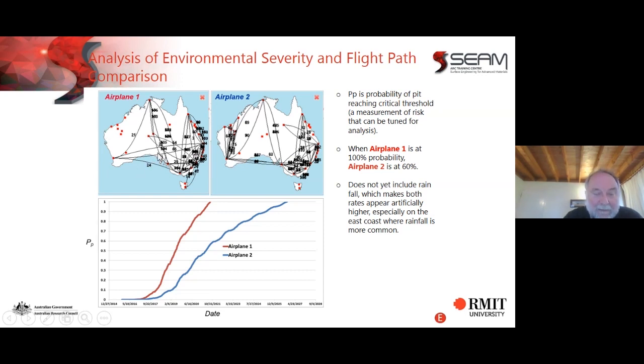So we put that into our system, and we found that this was the probability of pit growth from corrosion on aircraft 1 in the red, and in the blue is aircraft 2. So you can see, just as we were told, that the corrosion was occurring much faster on aircraft 1. Analysing the pattern, it's because aircraft 1 has these excursions down much more into southern Australia.